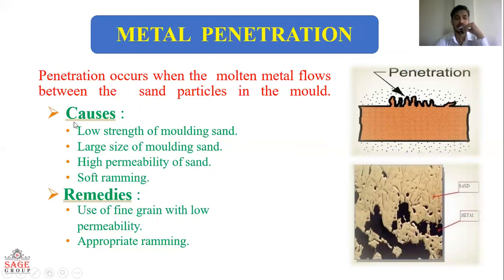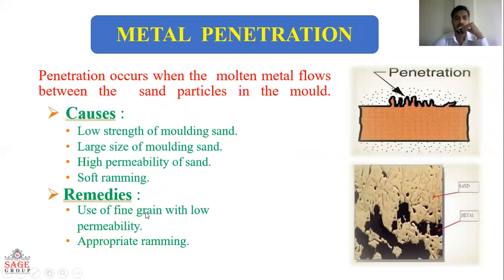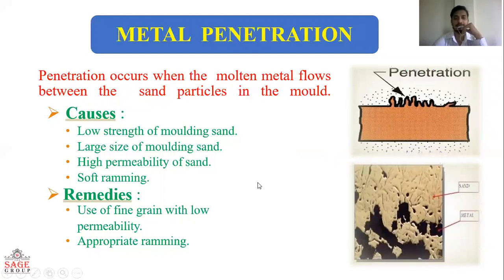These are the causes of metal penetration. Remedies: use fine grain sand with low permeability and appropriate ramming to avoid metal penetration in casting.